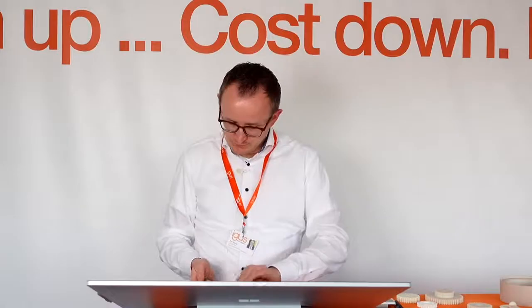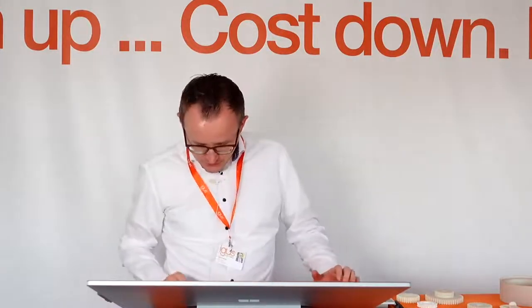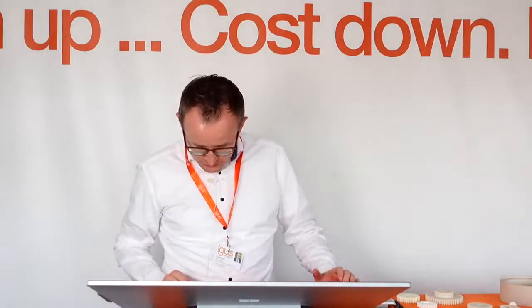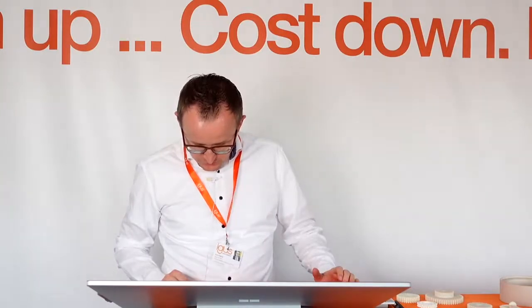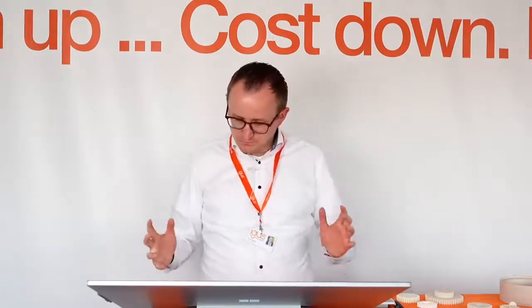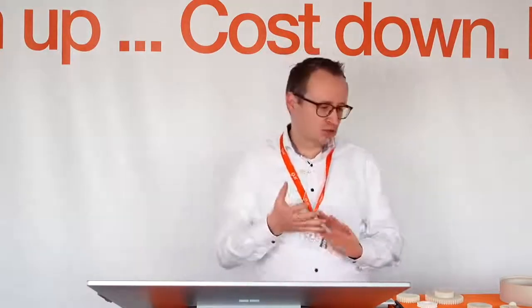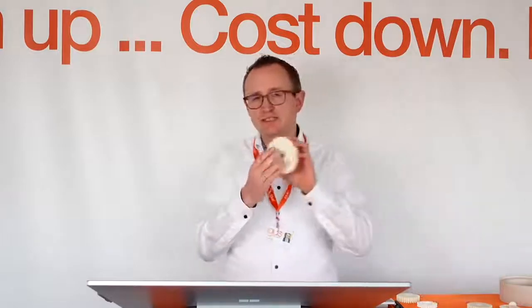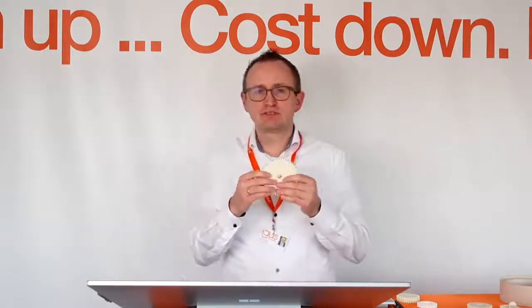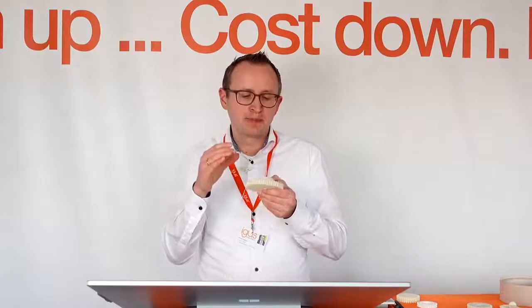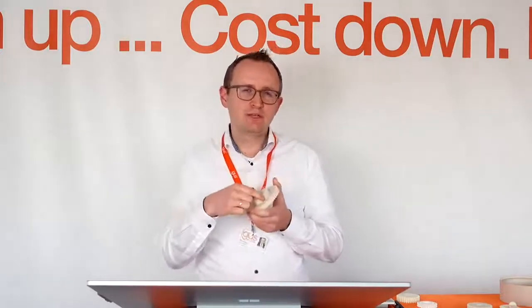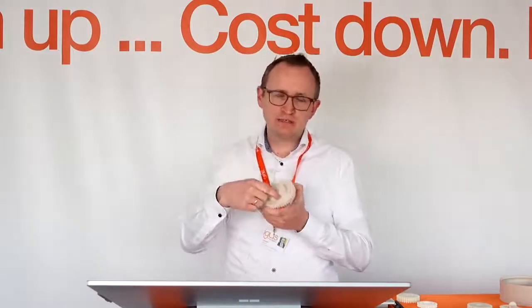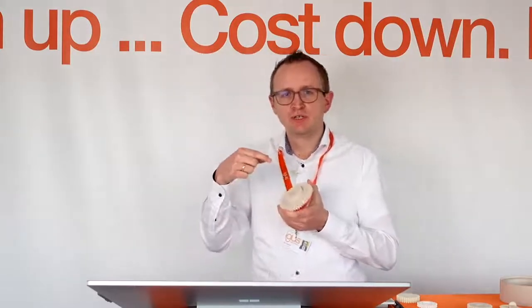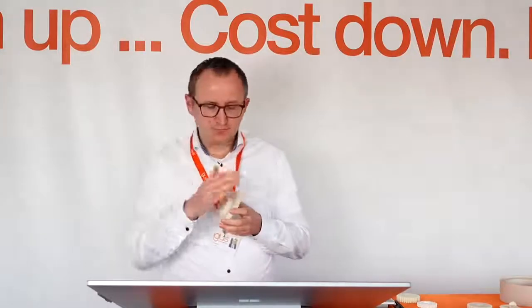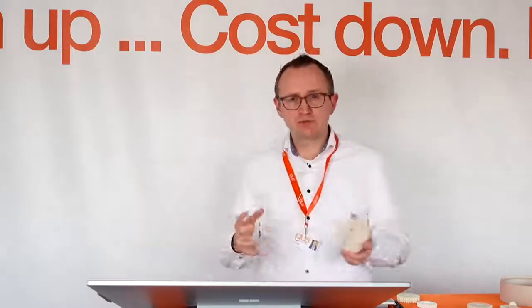What tolerance is achieved with the SLS process if you want to get a good fit on the shaft? Very good question. The tolerances we achieve with laser sintering are plus or minus 0.1 millimeters up to a size of 50 millimeters. If it's more than 50 millimeters, it's plus or minus 0.2%. That's what we can achieve without any rework.